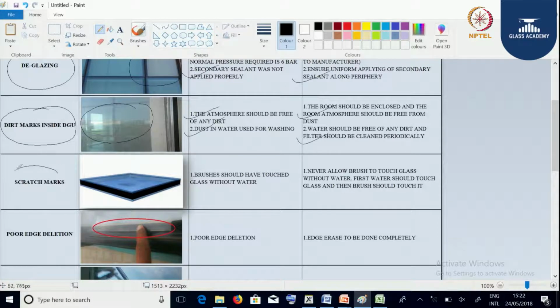Next you can see the scratches on the glass surface. This is because the brushes have touched the glass without water. We can overcome this issue by never allowing the brush to touch the glass without water. First the water should touch the glass, and then the brush should touch the water.